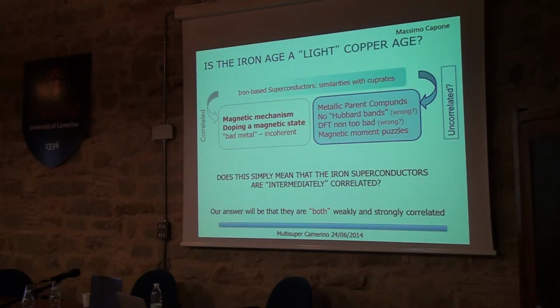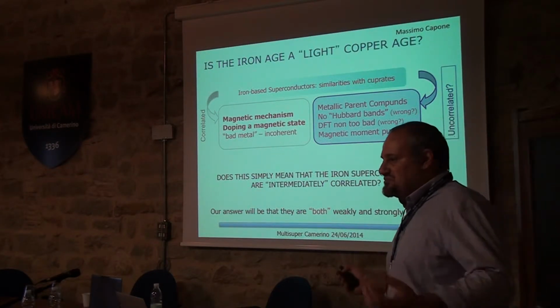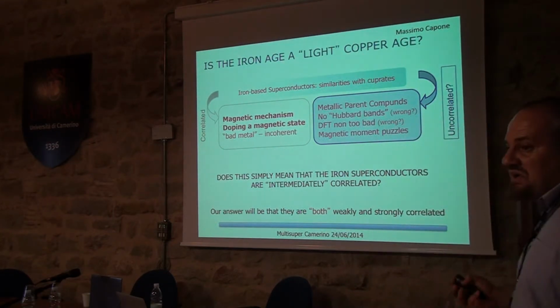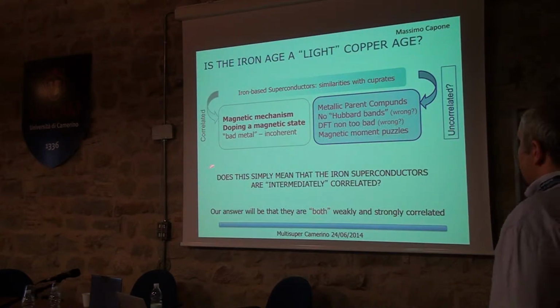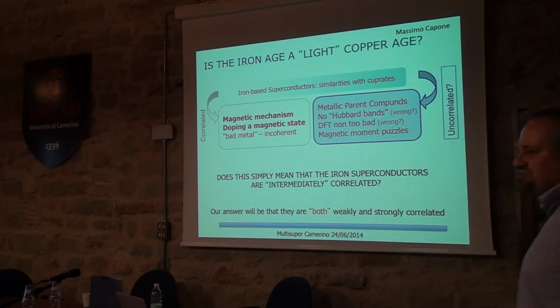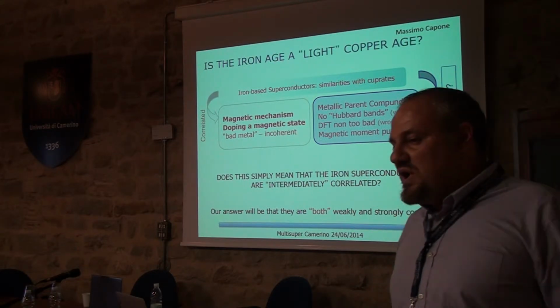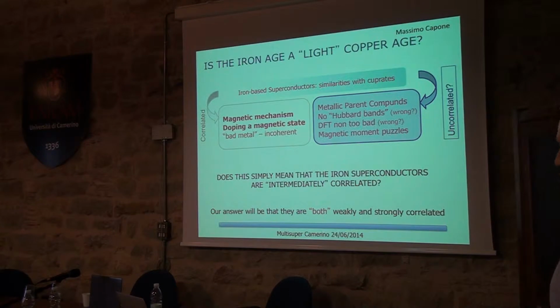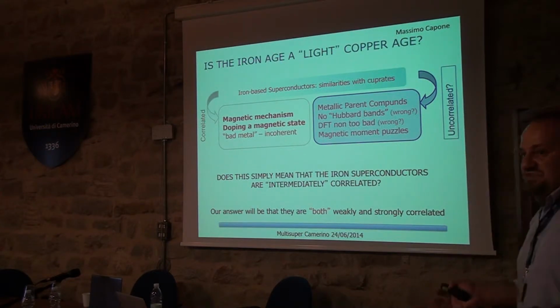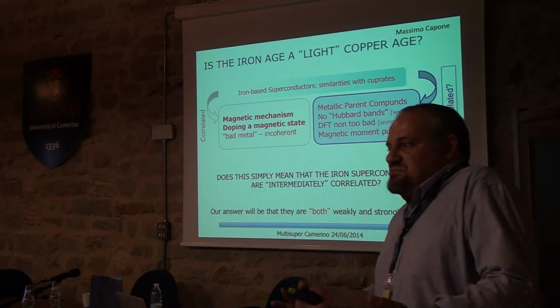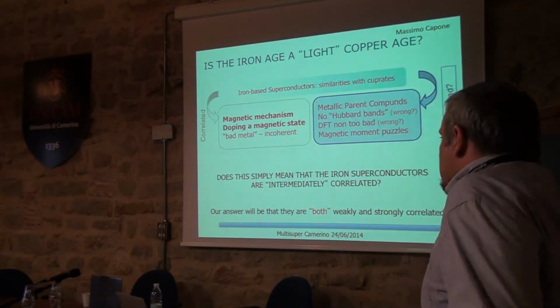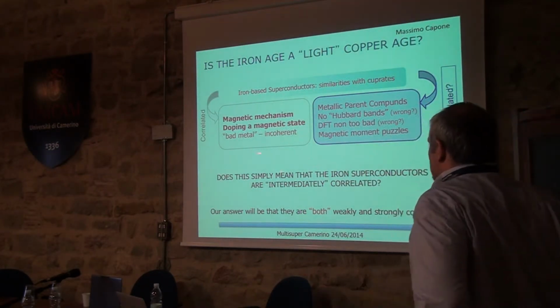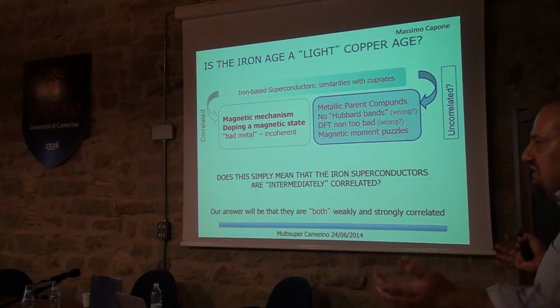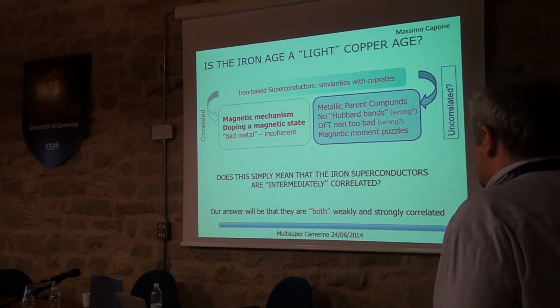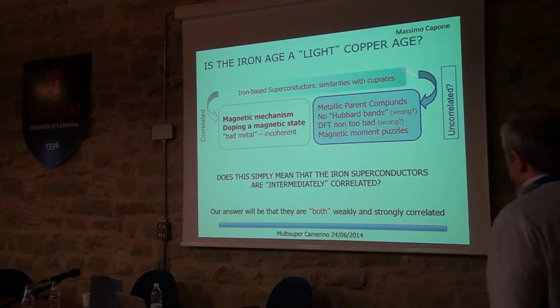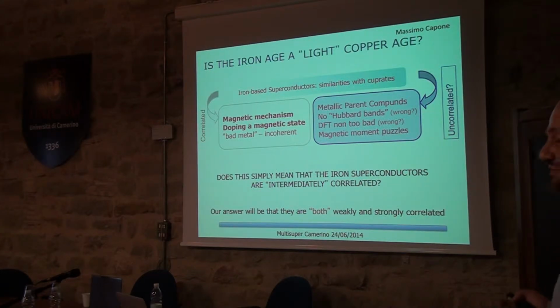Then everything anyway happens doping a magnetic state. So this magnetic state is likely to play some role. And that this metallic state is not a good metal. You can see it in many ways, the scattering rate that Sergei was mentioning before, or even simply the renormalization of the bands by a factor of 3. These are all things that point towards something where the metal, whatever it is, is not the ideal metal of the standard superconductors. On the other hand, there are aspects that point towards a different direction.